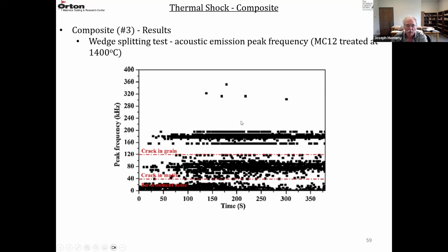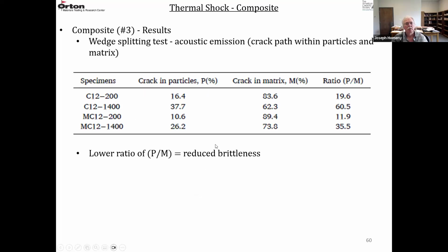So they can use acoustic emission not only to see how many fracture events are taking place, but the magnitude of those events. They can split it into fracture within a grain or fracture in the matrix. So they can get a percentage here, the cracks in the particles, capital P%, and the cracks in the matrix, capital M%, and take the ratio of P over M.